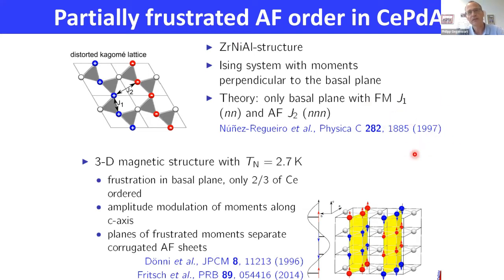more than 25 years. And in particular, the neutron scattering experiments revealed that there is an antiferromagnetic state developing at 2.7 Kelvin, which doesn't involve all the cerium sites, and which leaves one cerium site fluctuating, not participating in the long-range order. The order consists of such corrugated antiferromagnetic sheets, which possibly then result in frustration on this middle position. So we have in each plane a quasi-ferromagnetic coupling along this direction, and it's believed that those spins here do not order because they undergo the geometrical frustration, as indicated here.